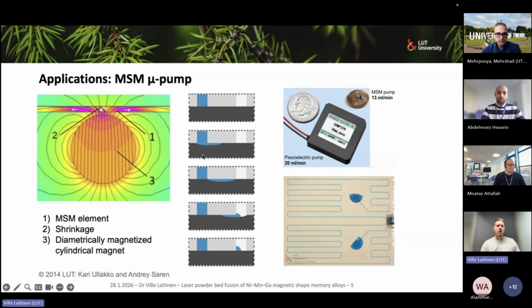Now if you place a liquid/gas tight seal on top of the material and then two outlets, for example one like this and one under there, you can use this undulation to travel between these two outlets and move liquid. Of course, if you rotate this magnet in a different direction, then this undulation will move in the opposite direction. So it's reversible pumping. You can pump in two different directions simply by switching which direction this magnet is rotating under the element. So that's the basic principle of the MSM micropump.